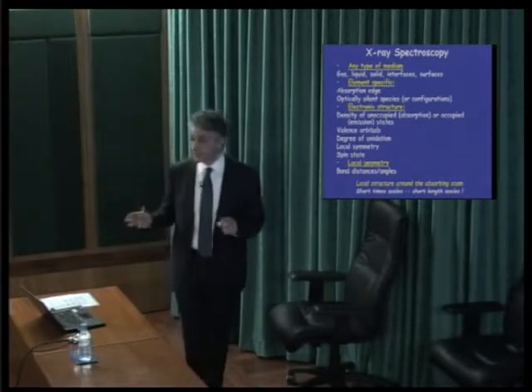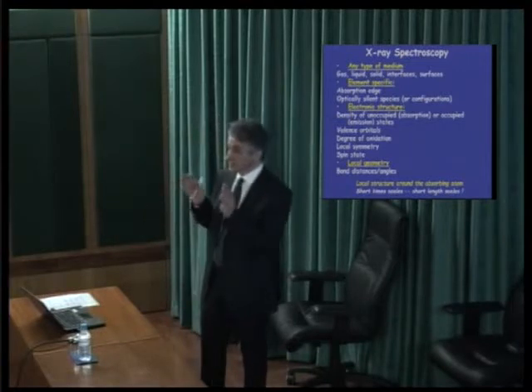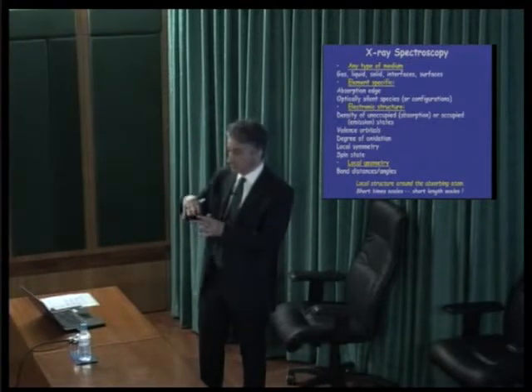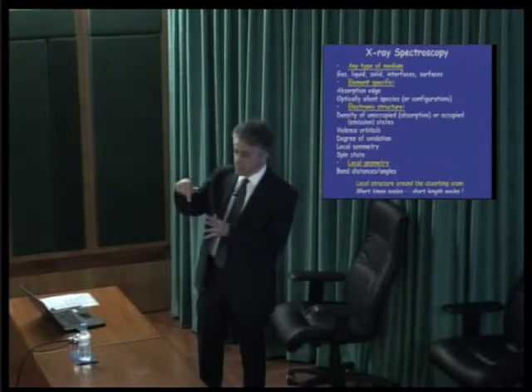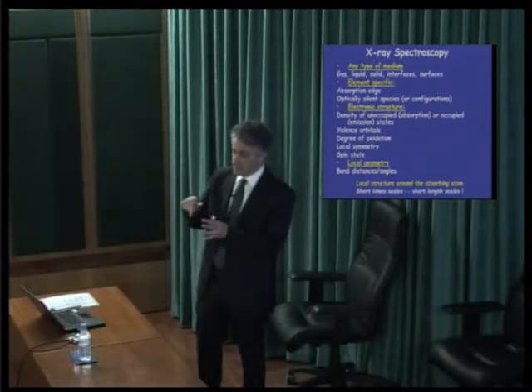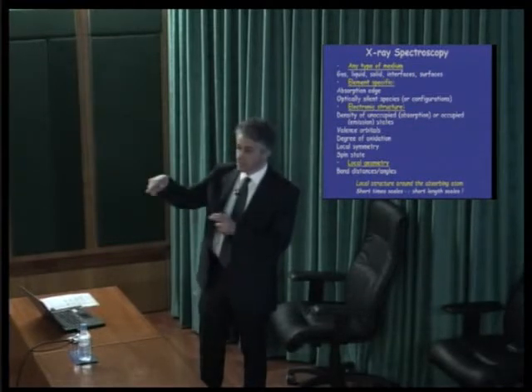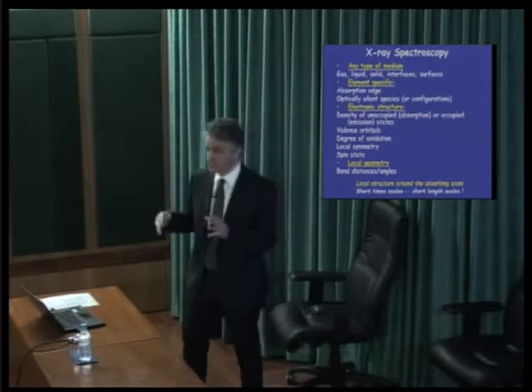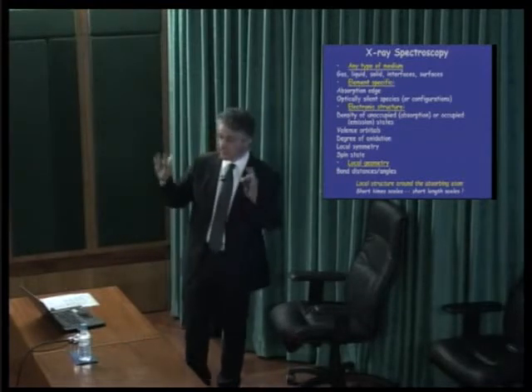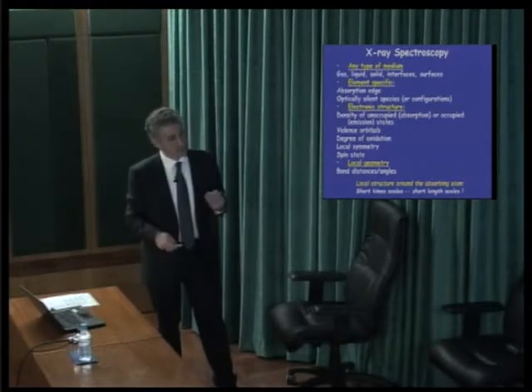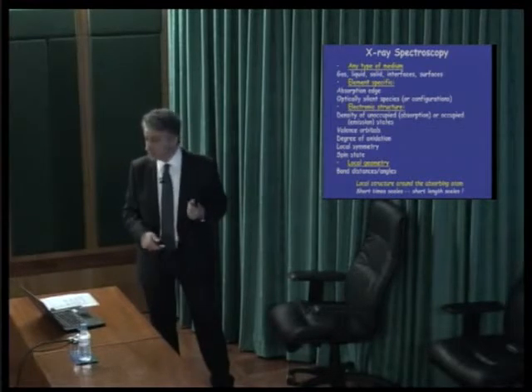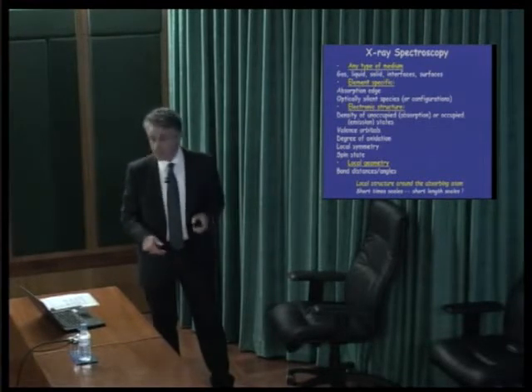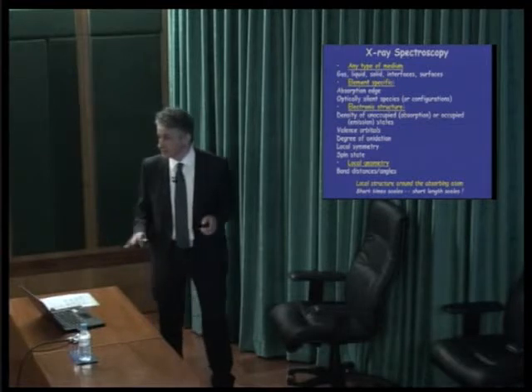Now, the big difference with X-ray diffraction is that it's a very local probe of the structure. You can only look at what is around the atom that is absorbing the X-ray, and maybe one shell or two shells, but not beyond. And that's a big difference with X-ray diffraction, which gives you the global structure. However, if you're interested in short time scales, then short length scales are fine. So we're in good shape.